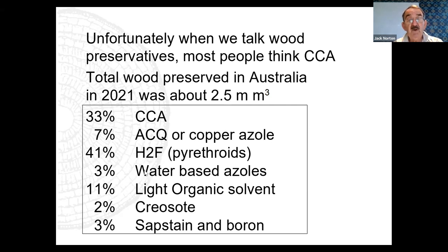Water-based azole is a different type of preservative. Light organic solvent preservative. Unfortunately, some people call it LSOP. It's not right. It's LOSP, light organic solvent preservative. That's for preservatives dissolved in organic solvent. And this is sapstain and boron. Sapstain is the blue stuff you've seen on pine. Queensland pine is particularly prone to this sort of stain, more so than radiata. And boron preservatives are only for lyctid susceptible or beetle susceptible timber.